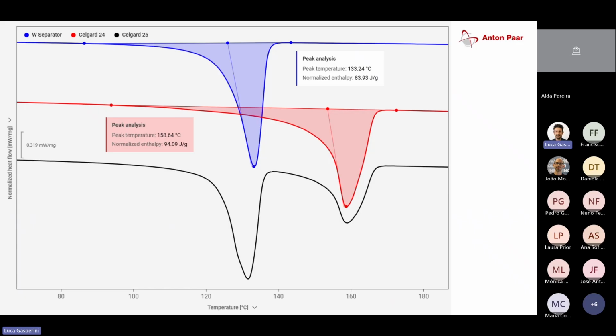And by running the DSC, we received one with a melting peak at about 130 degrees, the other with the melting peak at about 160 degrees, and the third one with actually 2 melting peaks. By having the knowledge of how polymers melt and how they behave, we can tell that the first one, the blue one, is made out of polyethylene. The red curve comes from a material that is a pure polypropylene battery separator. And the last one showing us the 2 melting peaks is a sandwich material where both the components are included. So the polyethylene melting at the lower temperature enables an early thermal shutdown in case something goes very wrong. But at the same time, the polypropylene gives the battery separator a higher structural integrity. Thus, by blending or creating a multi-phase separator, we can give it the final properties that are needed for our application.